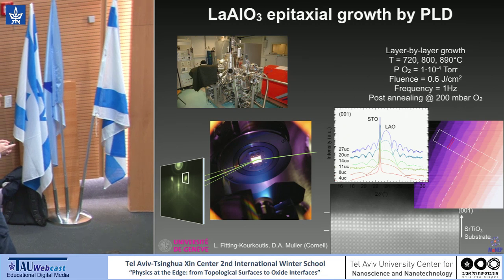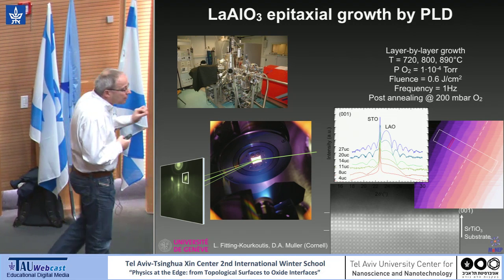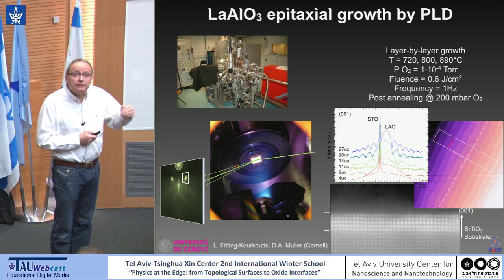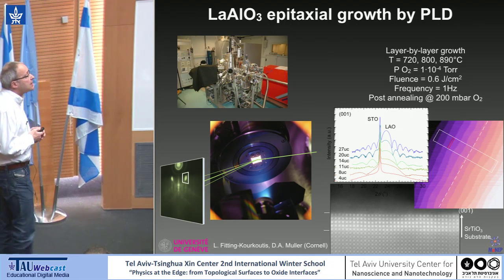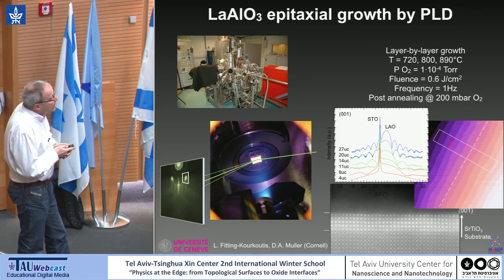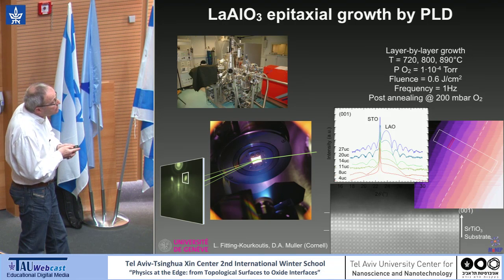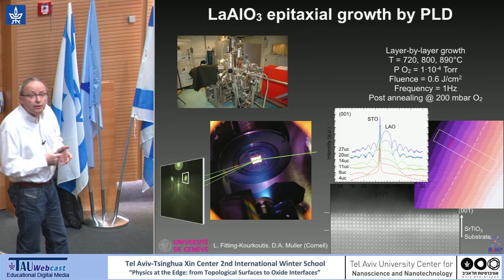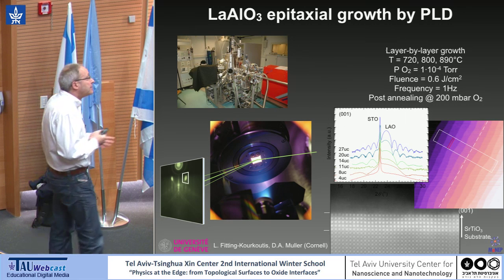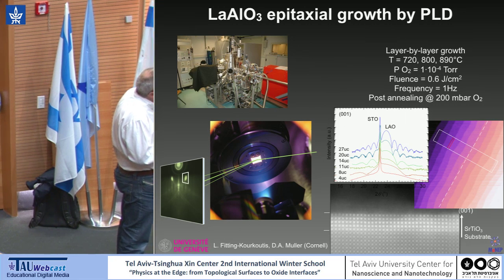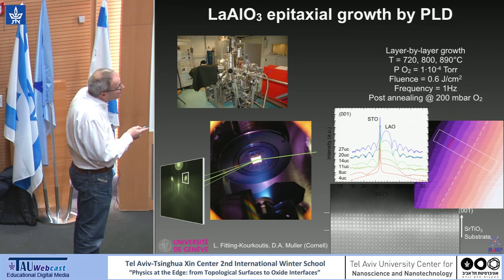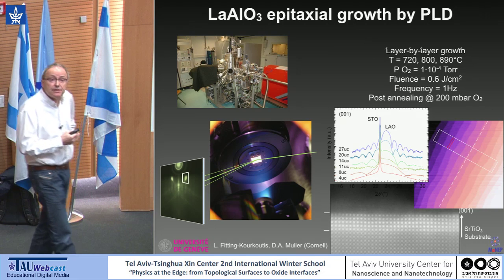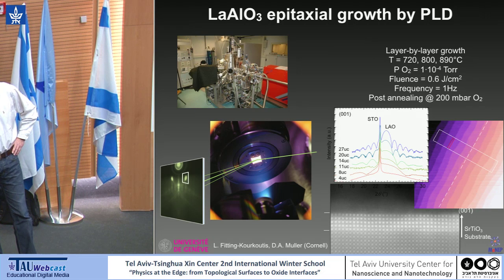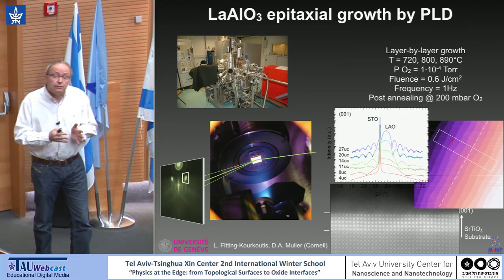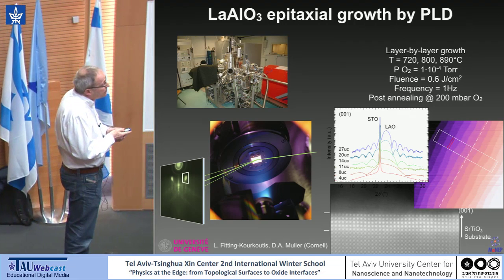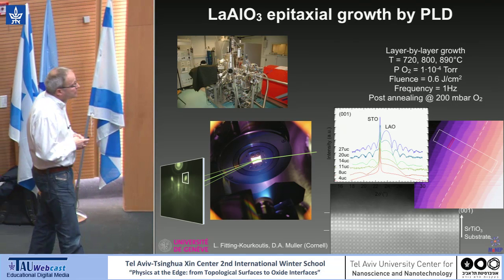When we grow this lanthanum aluminate layer, we use a technique which is called RHEED, which allows the layer by layer growth to be followed, and which also allows the thickness to be very precisely measured. And when you end the deposition, you can use atomic force microscopy to look at the surface. You see steps and terraces, which mimic the structure of your substrate. You find for relatively thick films these additional fringes on X-ray diffractograms, which allow you to check that the thickness of the lanthanum aluminate layer that you got from the RHEED is indeed the correct one, and you can also do some TEM to check the surface and the interface quality.